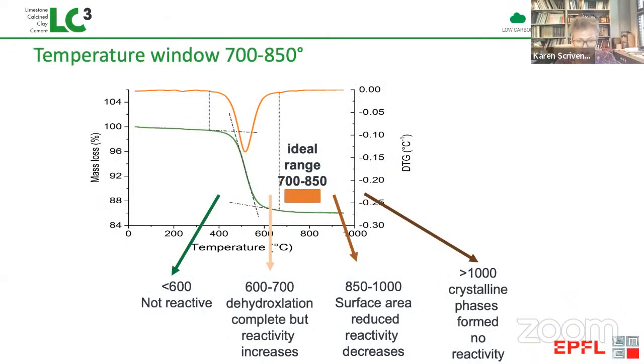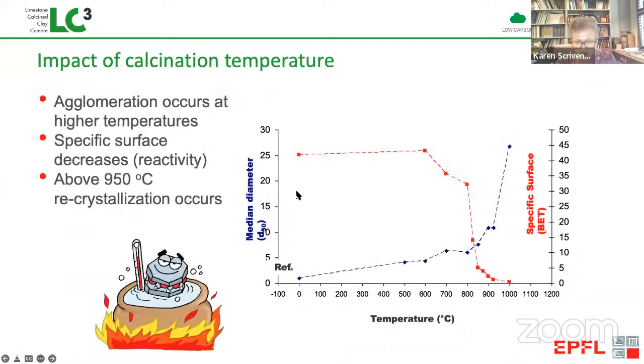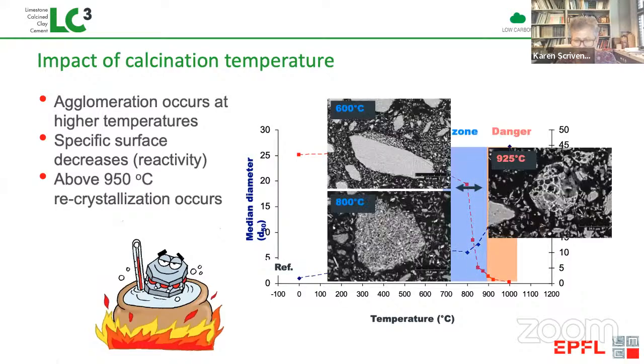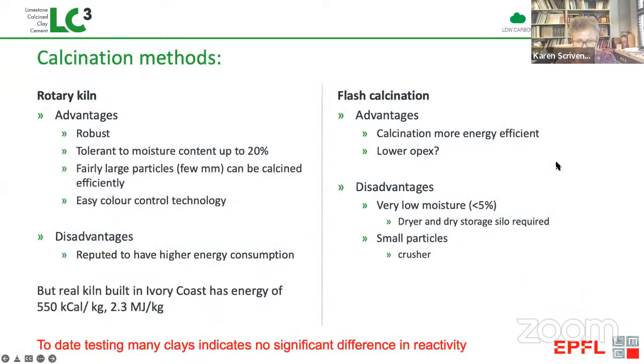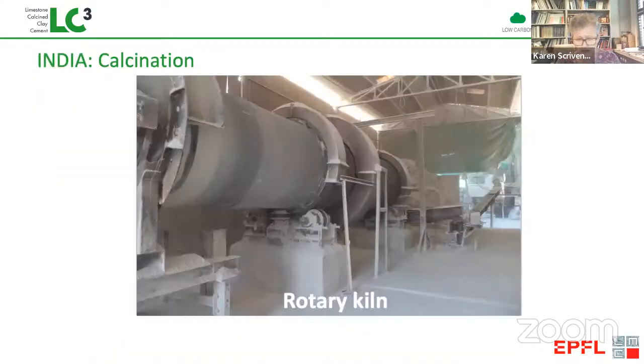For the calcination, you need to calcine in this range 700 to 850. If you go higher, then you tend to get a decrease in reactivity due to some sintering. But you can do this calcination either in the rotary kiln or in flash calcination. Both equipments have their advantages and disadvantages, but we really don't see any major impact on reactivity.